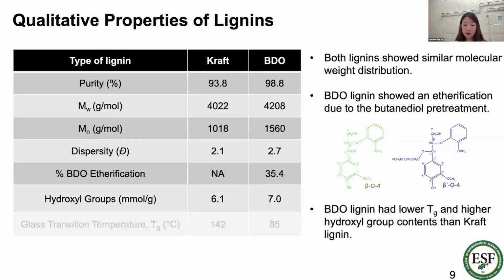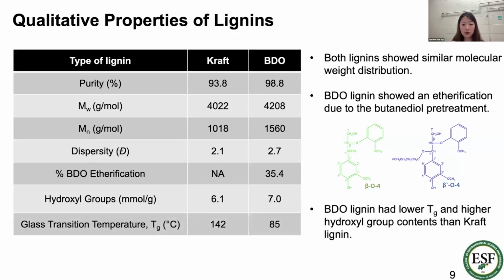And the thermal properties are also important for the further process of polymerization. So we measured the glass transition temperature, and the kraft lignin showed 142 degrees Celsius, and BDO lignin showed a lower glass transition temperature, at 85 degrees Celsius.